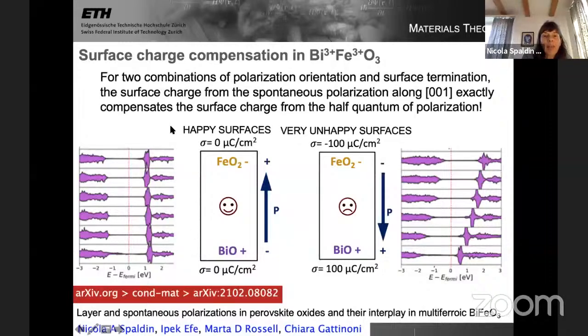And you can see in the happy situation, there's no internal electric field. The valence band and conduction band, the Fermi energies here, are constant through the film. Whereas in the unhappy case, there's a very large internal electric field, and even at the surfaces, it becomes metallic to screen this electrostatic instability.